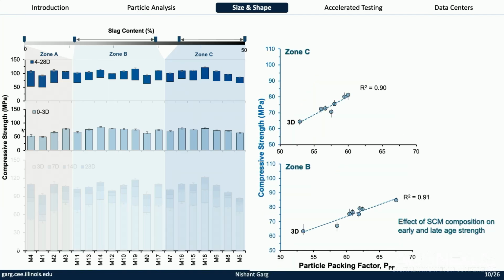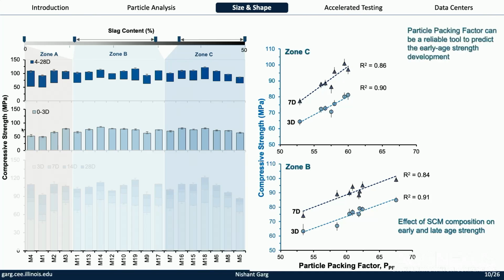But then really what is more interesting here is if we plot the strength versus the packing factor, again, you can see almost a linear increase in strength as you get to better packing, right? So really optimizing the packing can give a meaningful difference in strength. Again, this is in megapascal. When I convert it to PSI, I can do the multiplication by 145, but these are large numbers.